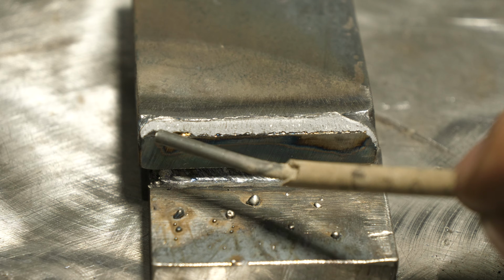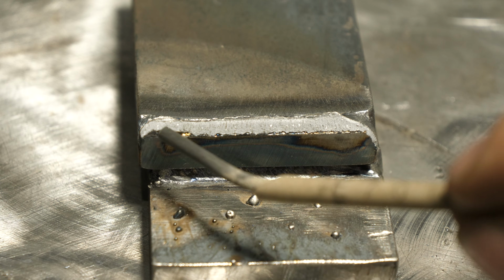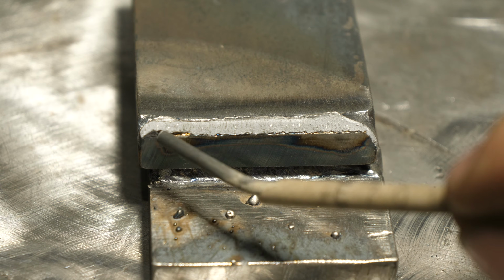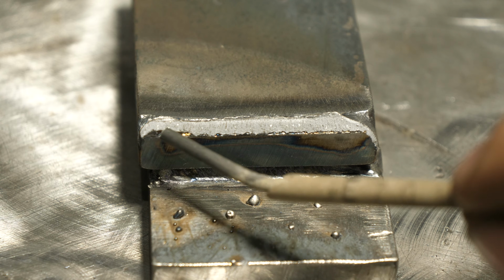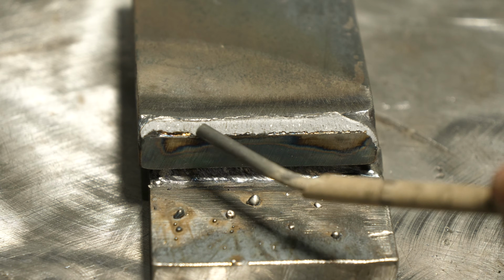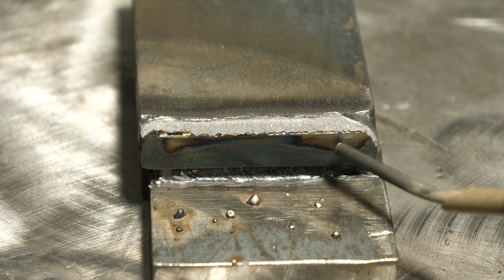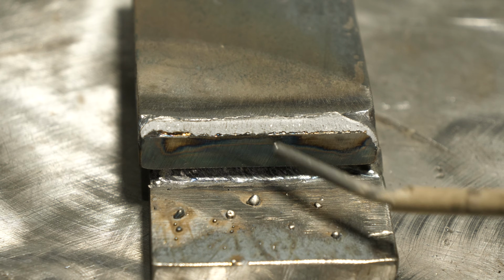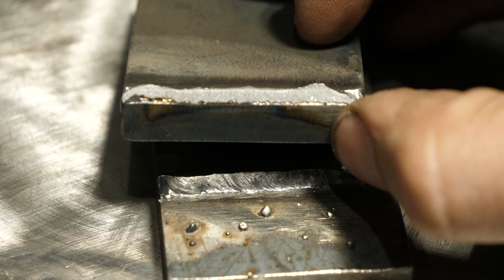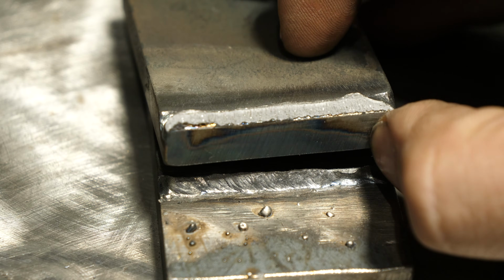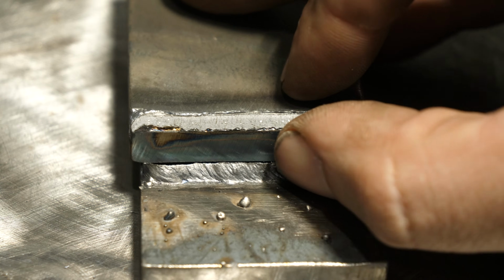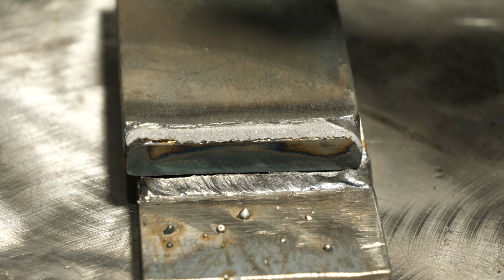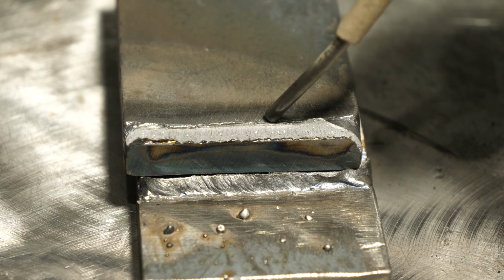And if you look here, pretty typical, somewhat of a lack of fusion at the start of the rod. I did have hot start enabled, but my machine that I was running on is either on or off. You can't adjust it, so this is very typical. Now, when you get back to over here, there's no evidence that the original plate edge was even fused. You can see the original plate edge there. So no root fusion, which is exactly what I expected with 7014.